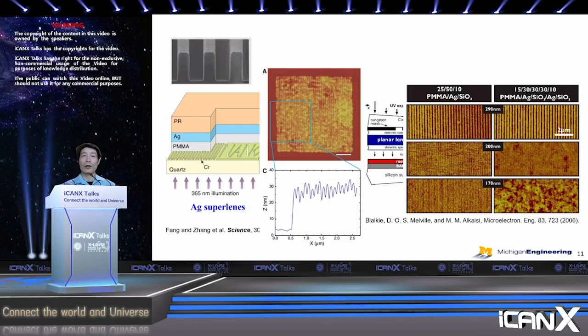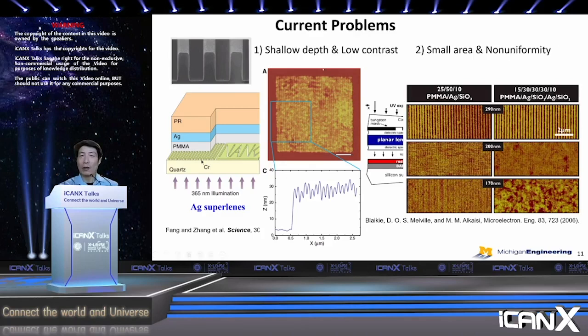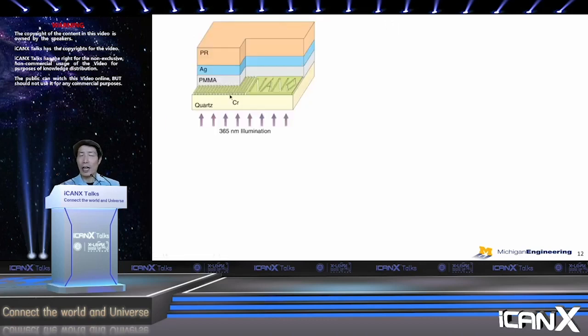Okay. So the problem is very shallow and low contrast. And small area, even small area is not uniform. Okay. So we have to understand why this is the case. Now, the shallowness can be easily understood. Because you're using UV light, the features of the mask are much smaller. So diffracted light cannot propagate very far. They're all evanescent waves, meaning they decay exponentially from the lens, right? So therefore, you can only expose the photoresist near the silver film, okay? That's why it's shallow, right?